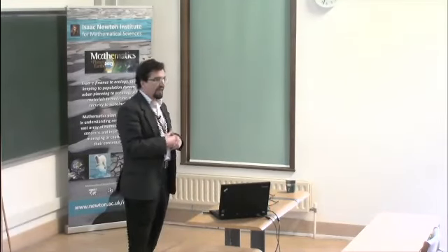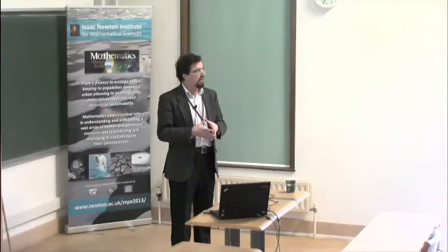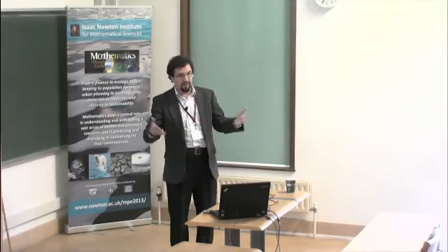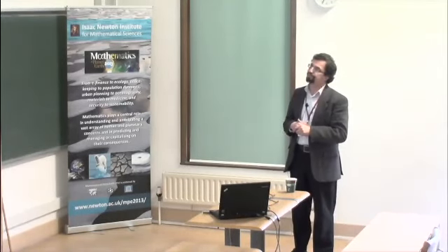So, as Tim explained, the simplest phase in liquid crystals, the so-called nematic, is just a fluid in which you have orientational order of anisotropic molecules or aggregates of molecules. And we call this direction of preferential orientation the director. And in a uniaxial nematic phase, the director is also the optic axis. This is what makes liquid crystal textures so unique, and this is why we can reconstruct the director field by observing the liquid crystals under the microscope.